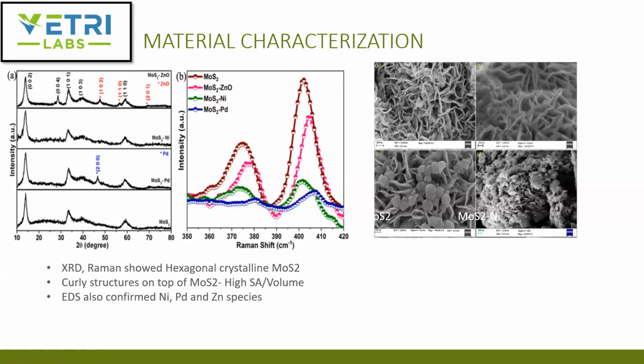Just to confirm, they did an EDS as well, and that confirmed that they did get structures with nickel, palladium, and zinc. On the right side, those are the shapes obtained with each of the materials. So that's moly sulfide, and each of these materials has curly structures. It shows you the high surface area to volume with these materials. So they've shown that they have coated and functionalized each of the structures with nickel, palladium, and zinc on top of the moly sulfide. Next slide.